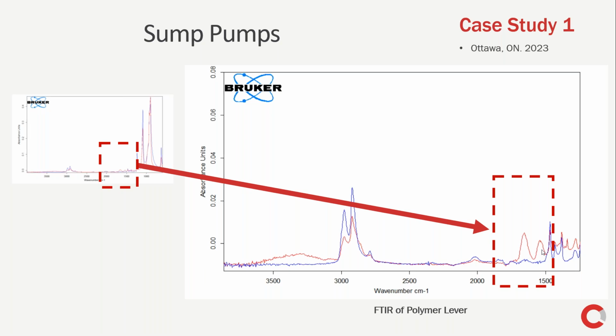So our analysis pointed to a possible off-gas from either some of the glues used to seal the float switch or some of the other components that were off-gassing inside. And at that point, we had enough evidence to close our file, and our client was able to recuperate on that claim. But we could have done additional testing, such as GCMS, in order to understand the particular type of material or compound that was causing that damage, and then further prove that it was some off-gassing material.